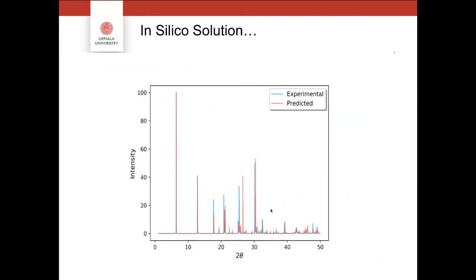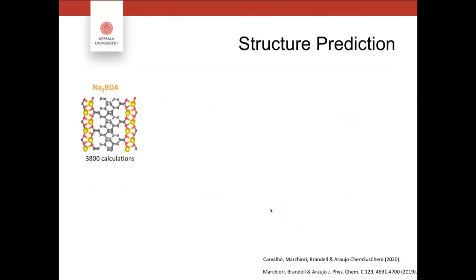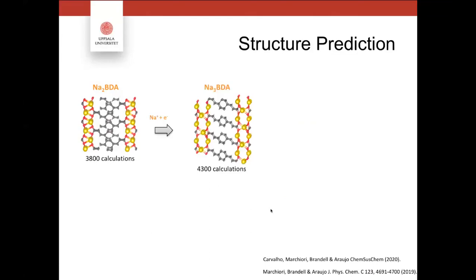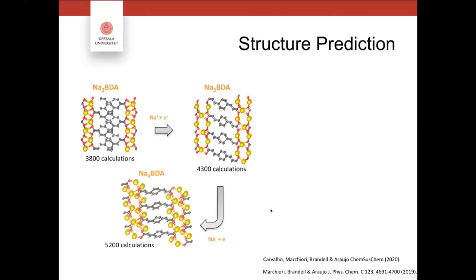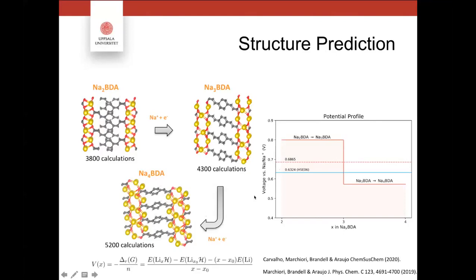I can go beyond and start with my initial pristine structure and start making prediction of the structure after insertion of sodium ions and electrons in the structure, what would not be very easy to obtain from the experimental point of view. This is, for instance, the first sodiation step, and then the second sodiation step. These are the number of calculations that are necessary for this prediction. And from there, we can basically predict the voltage concentration profile, and this displays excellent agreement with the 0.6 volts obtained experimentally. So this is our first framework.